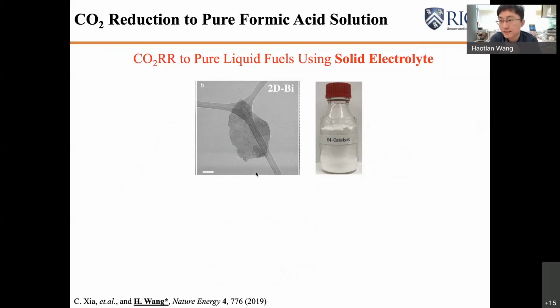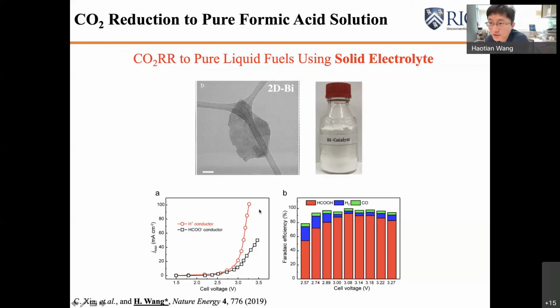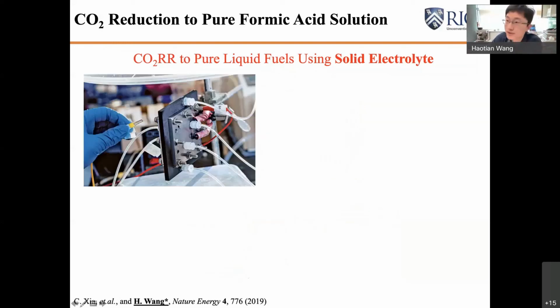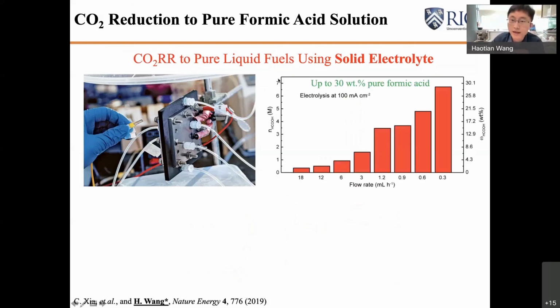So by doing so, we utilize a two-dimensional bismuth catalyst as a representative example to generate the formic acid. And as you can see, using the proton conductors, which is the solid electrolyte conductors, we can get more than 90% formic acid selectivity. So that guarantees a very good catalytic activity. And this is the picture of our cell, cathode, anode, and sitting in between, there is a porous layer of solid electrolyte. And also, it's very obvious if you slow down the DI water stream, but maintain the formic acid generation rate, we can accumulate very high concentration of high purity formic acid. As you can see, we can get up to 30% formic acid in its very pure form.